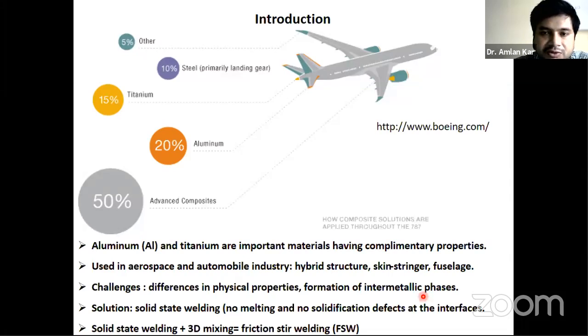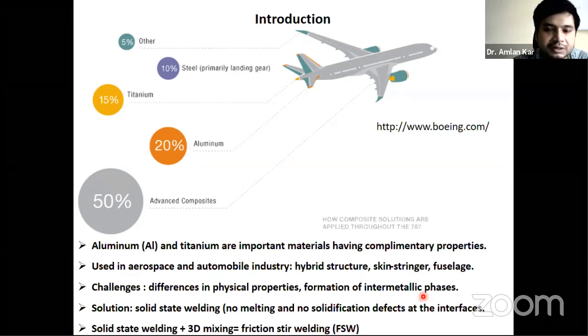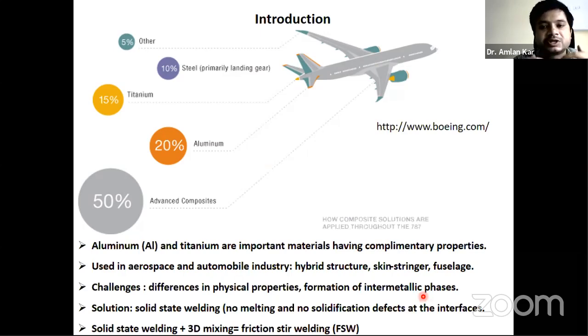And since this process is called a solid state deformation process, whatever temperature is developed is a friction based temperature. And you know, the friction at the melting point is close to 0. If you assume that the temperature is increased to the melting point, then friction will reduce, and therefore there is a reduction in the flow stress. Okay, if flow stress reduces, then there is an increase in the coefficient of friction. So these two phenomena actually counteract each other, and therefore